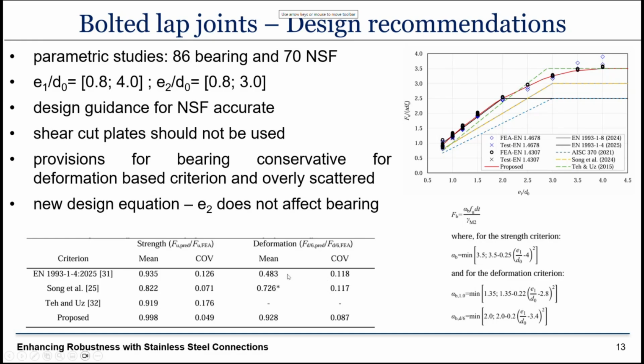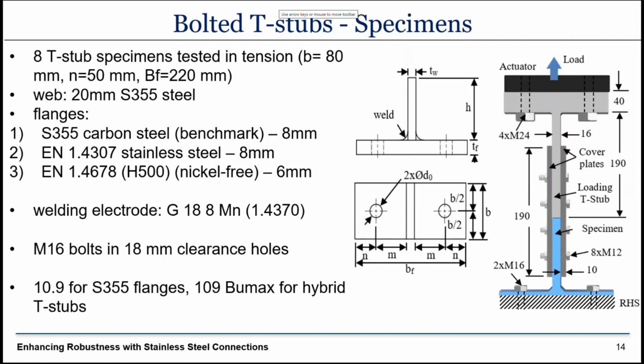So our proposed equation gave a much better agreement with the obtained results, with a significant reduction in scatter from 12.6% in the current Eurocode version to 4.9% using our equations. So this was the part of the research dedicated to bolted lap joints. Now we will move on to T-stubs.